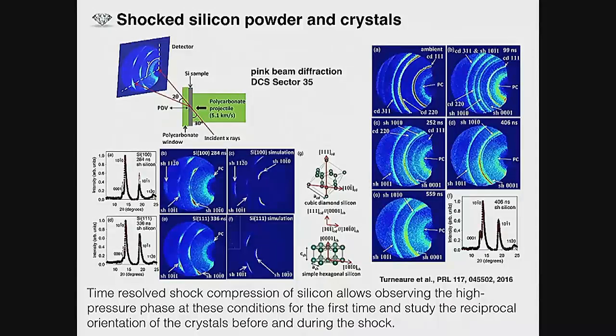This is a paper last year, one of the first papers out of the dynamic compression sector, and again, it is an element. Here is a schematic of the experiment. So you have a projectile, your sample, your windows. You have other probing techniques that would tell you what velocities are and hence pressures. And you have a detector. So your beam needs to go through these materials and look at the time scales of these diffraction patterns. So 99 nanoseconds, 200, and 600. So these are time-resolved diffraction patterns during a shock.